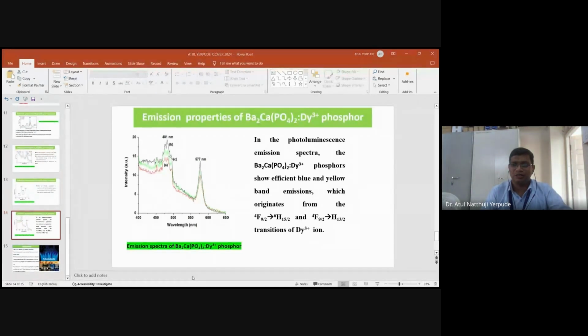This emission spectra consists of two characteristic bands, one located at 481 nanometer and another band located at 570 nanometer, which originate from the 4F9/2 to 6H15/2 and 4F9/2 to 6H13/2 transitions.